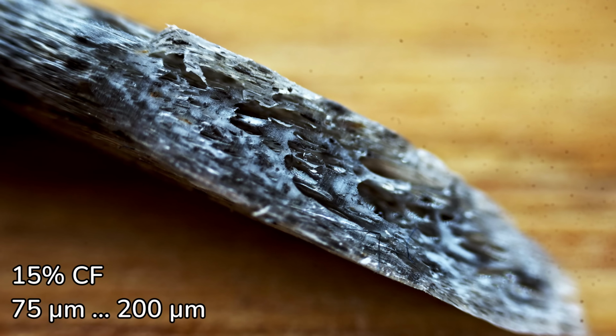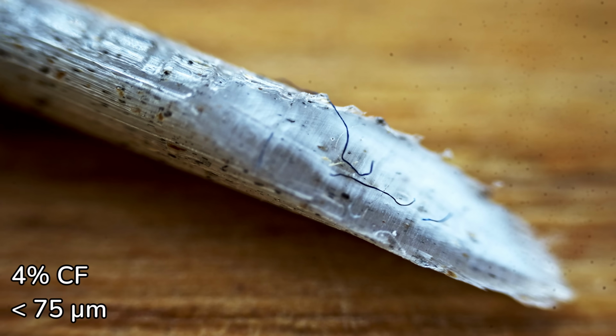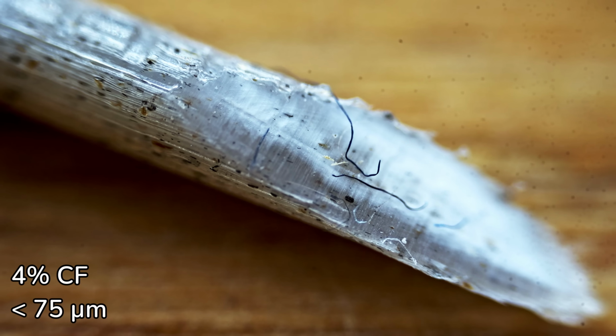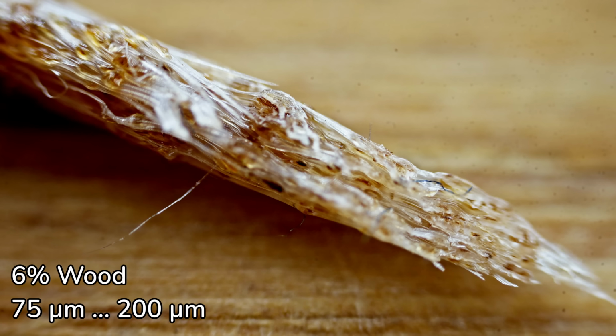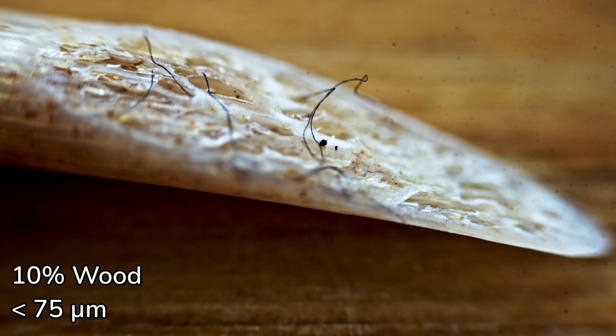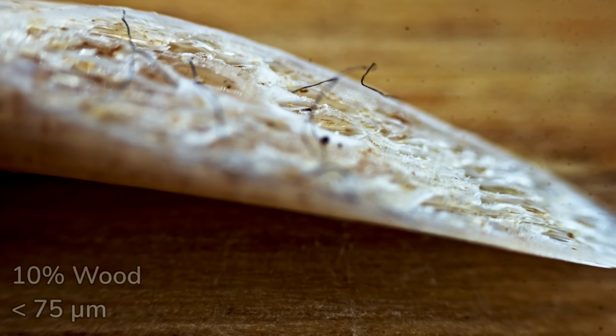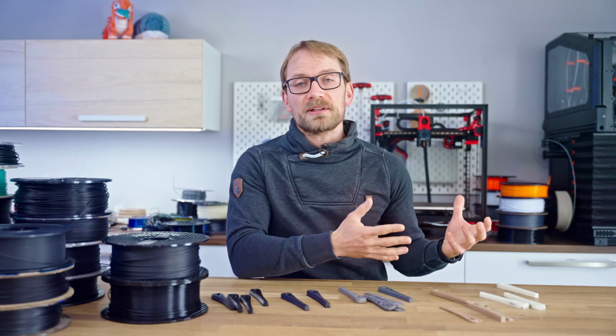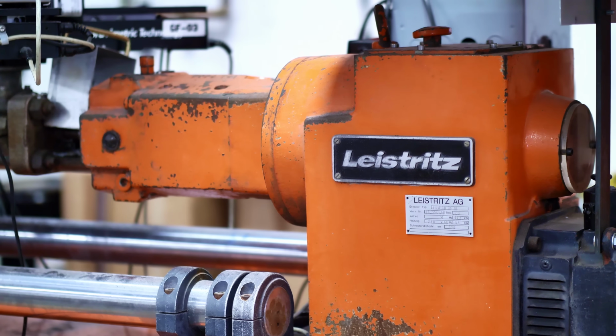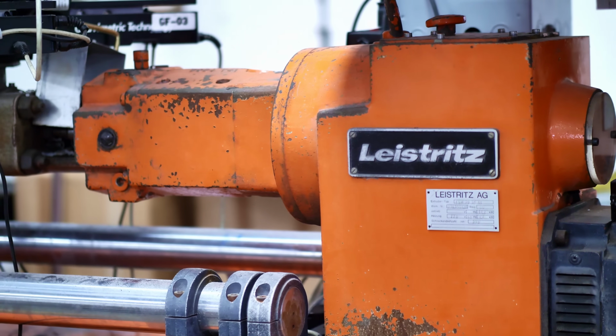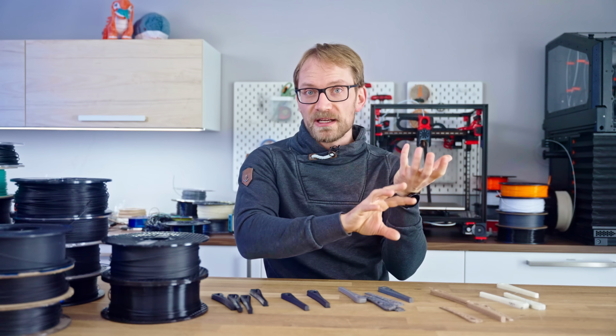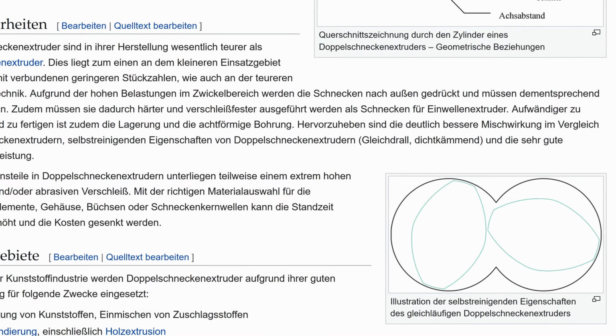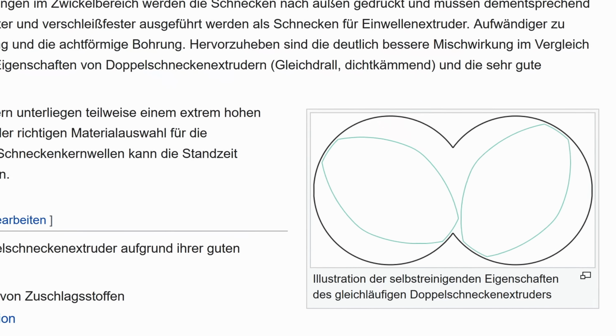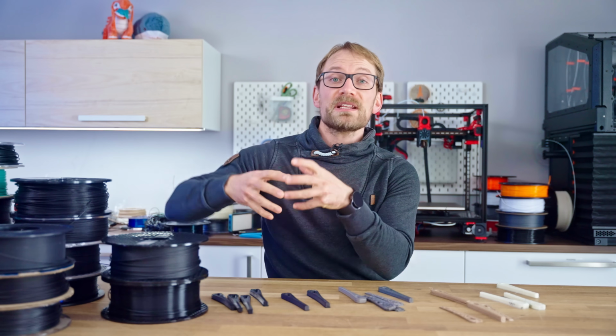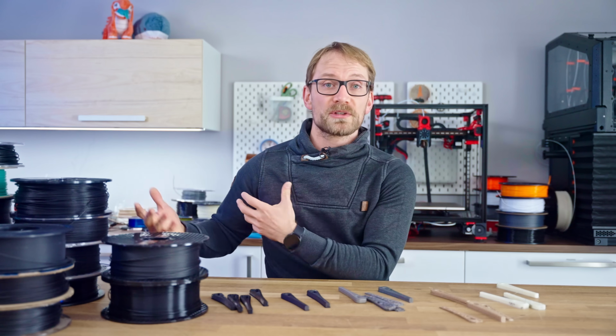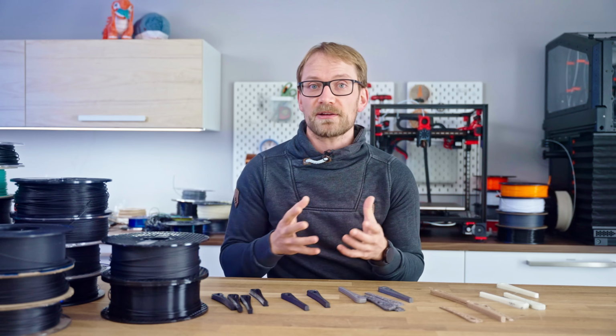A ball mill would still be the better choice for essentially smashing the carbon fiber bits into individual fibers, and then of course a filament extruder that's actually made for mixing and compounding would have helped too. Typically, when solid material like fibers or even colorant is added to polymers, it's first run through a twin screw extruder that only has the job of mixing, shearing, and kneading your plastic into a consistent compound first. The extruded material from that is then chopped into pellets again, and only then run through an extruder that now only has to worry about creating a consistently sized filament.